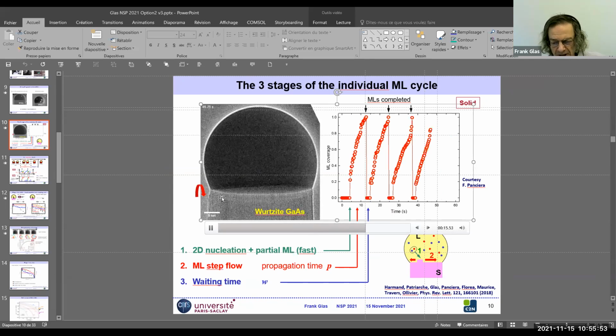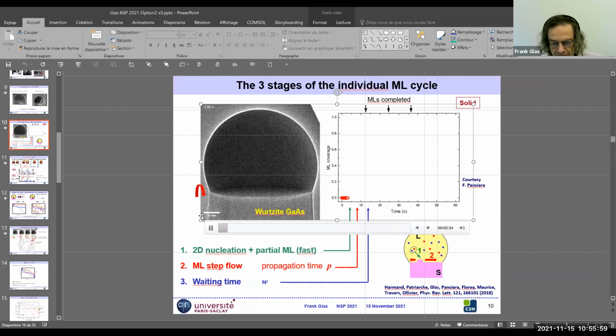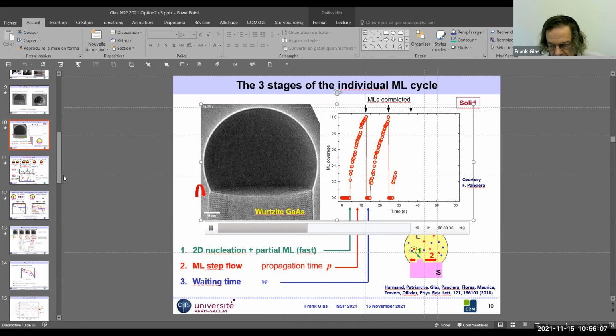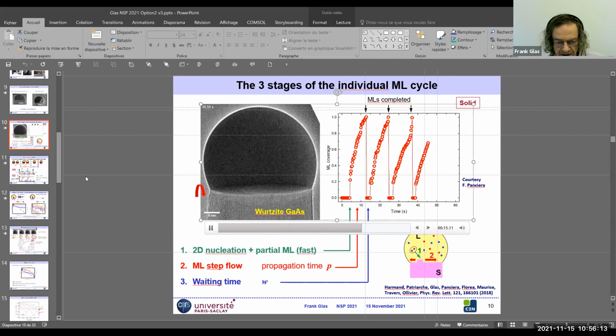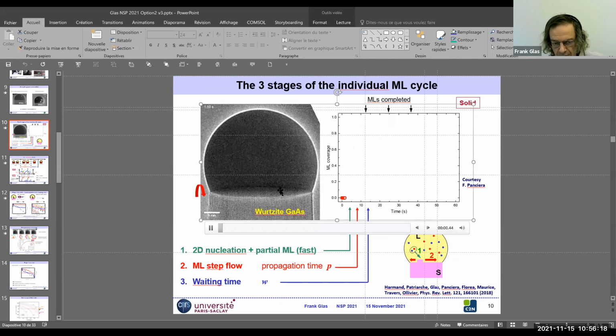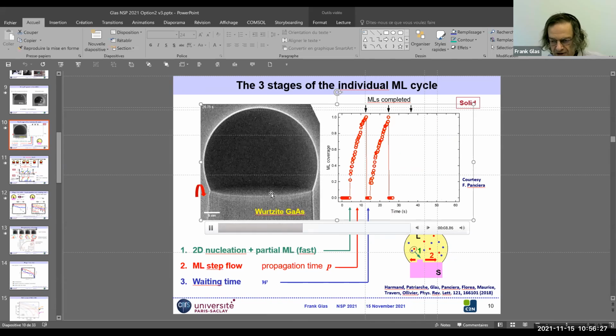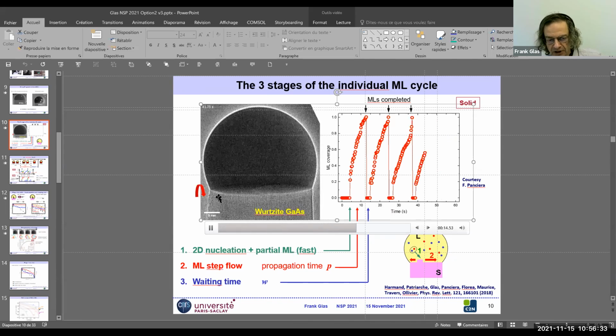I think we try to estimate... It's very difficult to have a 3D view, but we try to estimate the number of atoms which were transferred from the truncation to the monolayer, and that's of the order of the number of atoms in the monolayer. So experimentally, at least, it seems that the process of transfer can go on until completion. And I think also there we're going to be helped by the fact that the monolayer energy decreases non-monotonically. So it's interesting to transfer, same as when the transfer occurs from the liquid to the solid. Then I think it will be the same.